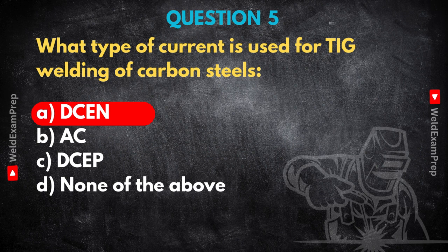And a side benefit is the electrode itself stays relatively cooler, which helps your tungsten last longer, doesn't burn away as fast. Now, just to compare, if you use DCEP, electrode positive, most heat goes into the electrode. You get very shallow penetration, and you'd likely burn up your tungsten very quickly. It's usually for very specialized things. And AC, alternating current, is the one we use mainly for aluminum and magnesium. That back and forth flow gives you a cleaning action to break up oxides, plus decent penetration. So for carbon steel TIG, it's almost always DCEN. Choosing the right current type is non-negotiable for a good weld. Absolutely fundamental. Match the current to the material, get it wrong, and things go badly pretty quickly.